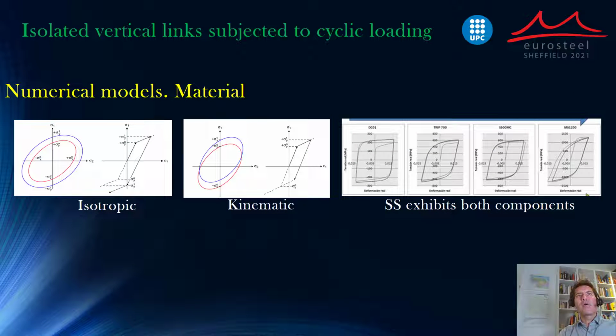Also, something to mention is that the numerical models that are implemented for stainless steel subjected to cyclic loading require proper understanding of the type of hardening that is included in the model. We can define hardening as isotropic, in which the yielding surface expands together with the uniaxial load that is given. It may behave as kinematic hardening, in which the yielding surface does not increase in size, but it moves according to the cyclic loading. But in this case, austenitic stainless steel exhibits both components. It exhibits isotropic hardening, but it also exhibits a certain degradation with the cycles, which needs to be reflected in the numerical modeling.